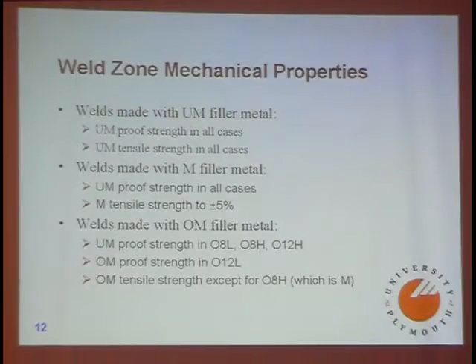So if you have a look at undermatched filler metal, you do a reasonably good job. So if you think you've made an undermatched weld, you have. Both the proof and tensile strengths are undermatched in all the cases we've looked at. If you look at matched filler metal, you get an undermatched proof strength in all cases, but more or less a matched tensile strength, about 5%. And so the concept of talking about welds as matched, undermatched, or overmatched is a little loose. And if you use the overmatched filler metal, you get undermatched proof strength in certain cases, and though these is overmatched 8 thick, low heat input, overmatched 8 thick, high heat input, that's the abbreviation system used. You get an overmatched proof strength in that one, and an, I guess random around in all the others, and an overmatched tensile strength except for that one, which is matched.